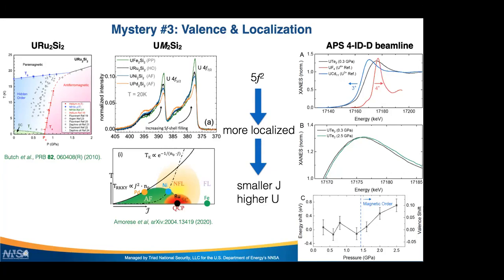And if we remember the discussion just now from the 1-2-2 family, that means that the system is somewhat hybridized. But under pressure, and this is panel B, there is a small but finite shift towards higher energies, meaning that we have then a more 5f2 configuration. So we're going with pressure towards a 4+, full 4+ configuration. So this makes a lot of sense, right? If we apply pressure here, we're going to a 4+ configuration. So 5f2, which is more localized, and then we have magnetic order. Again, counterintuitive if you just think of pressure as increasing hybridization, but not counterintuitive if you take the valence into account.